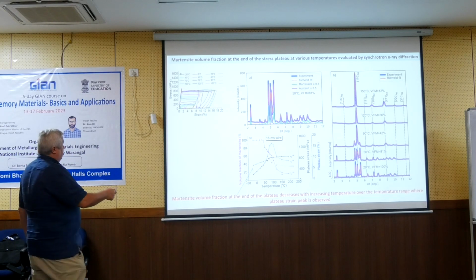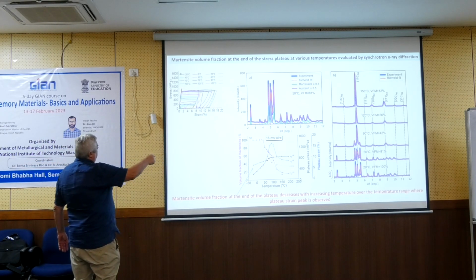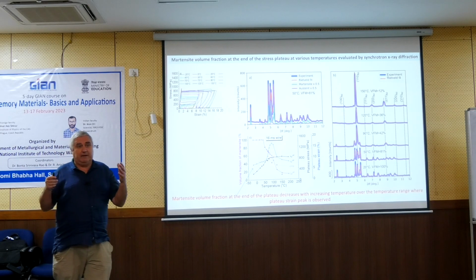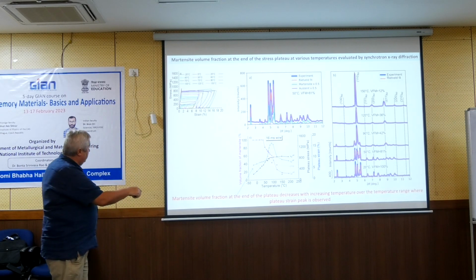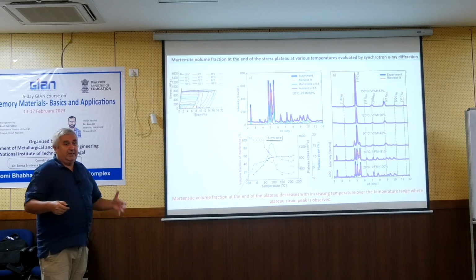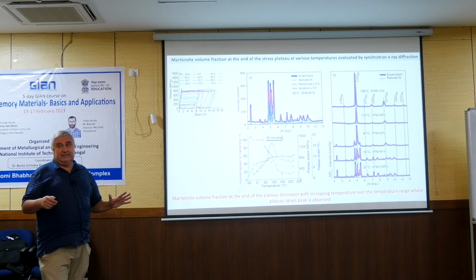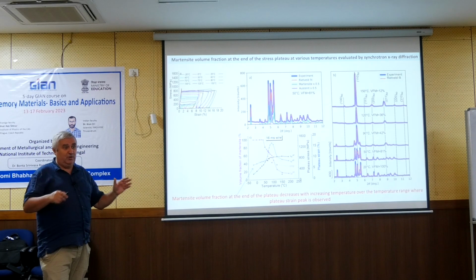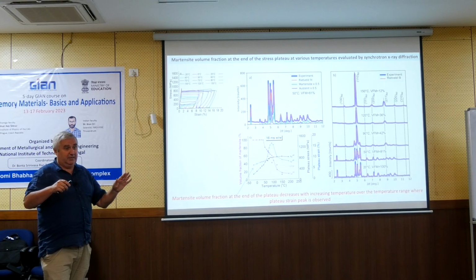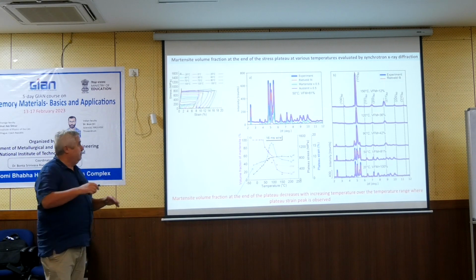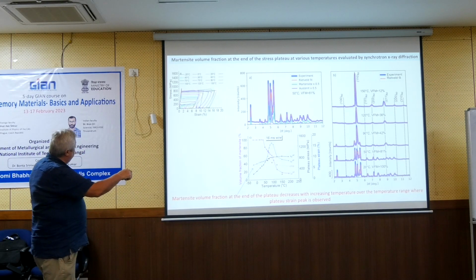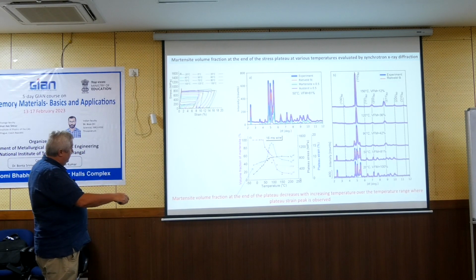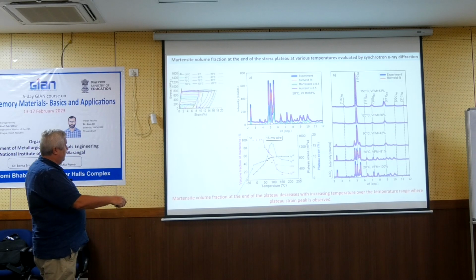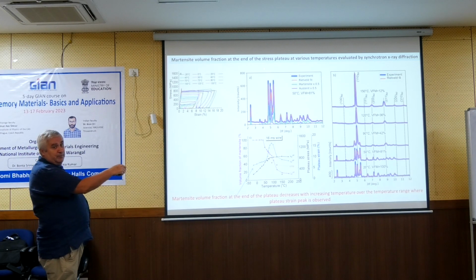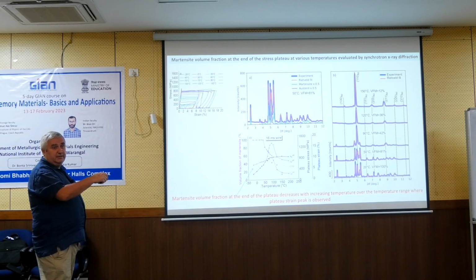So this is very important. We see the plateau, but the plateau never means that all your sample transforms to Martensite. At high temperatures, you have only 10% at the end of the plateau. Just a warning for you: if you see the plateau end, it doesn't mean 100% Martensite. On this curve, where the volume fraction is maybe 20%, if you continue, this phase transformation will continue upon further loading because you have lots of austenite in the wire.